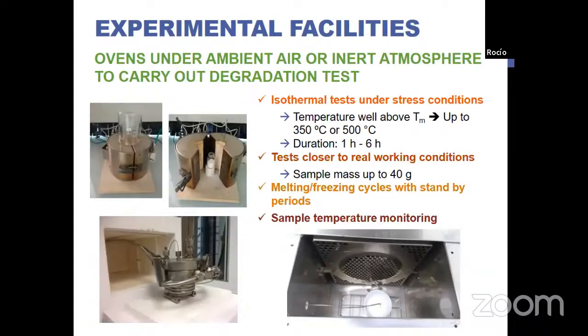What we have for this in our labs are, for example, ovens that can work in ambient air or inert atmosphere to carry out these degradation tests. So we can perform isothermal tests under stress conditions. Depending on the oven, we can reach temperatures up to 350 or 500 degrees. The duration of the tests is normally between 1 and 6 hours. The idea is to perform tests as close as possible to real working conditions, which means samples of up to 40 grams. Of course, real conditions require much more mass, but for the lab, I think 40 grams is quite okay.